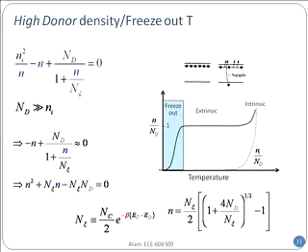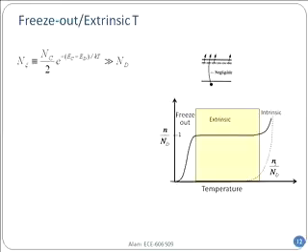Where is the temperature in this expression? It is in n sub xi. Why? Because n sub xi has the effective density of states sitting in there, right? Do you remember? The effective density of states is the density of states, which is temperature independent, multiplied by the width of the region which was occupied, and that changes at every temperature. So the place where the temperature is hiding in here, and why that gives you that particular curve, is because n sub xi is temperature dependent. Okay. So we could plot it out, and it's not a problem.